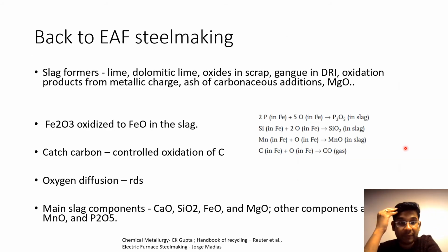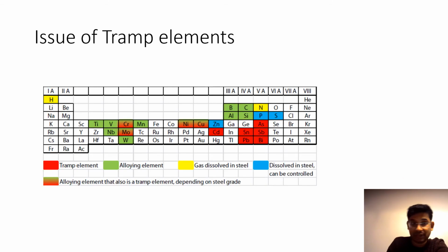Okay, so I'm not going to go a lot into the chemical details. It suffices to say that you have phosphorus, silicon, manganese, and all these things going into the slag phase by reaction with the oxygen. The oxygen diffusion is really the rate determining step, and because you want this slagging, as a kinetic enhancing step, they use slag inducers or slag formers so that you can have the removal of the gangue material and enhanced kinetics of this reaction.